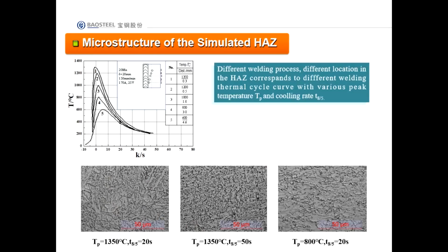We also characterize with t8/5. In this test, the samples are usually round. These are the simulated microstructures of coarse-grained HAZ. From this picture, you can know the peak temperature is 1,350 centigrade, and